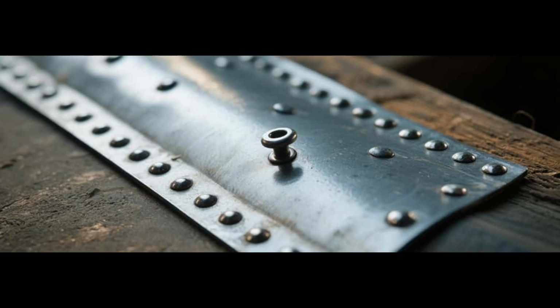The fuselage skin tears open along paths dictated by geometry, rivet patterns, and residual stresses locked into the structure since manufacture. What had been a sealed pressure vessel becomes, in an instant, a conduit for explosive decompression. The pressurized air inside the cabin escapes violently through the breach, driven by the pressure differential between the interior and the thin atmosphere outside. This outflow is not uniform. It forms a high-velocity jet, exerting aerodynamic forces on the edges of the rupture that can exceed the loads experienced during normal flight. Skin panels are peeled back, lap joints unzip. Frames and stringers, designed to share steady loads, are suddenly subjected to concentrated forces far beyond their design envelope. The fuselage, once a smooth cylinder, begins to deform asymmetrically under the combined effects of pressure loss and external airflow.